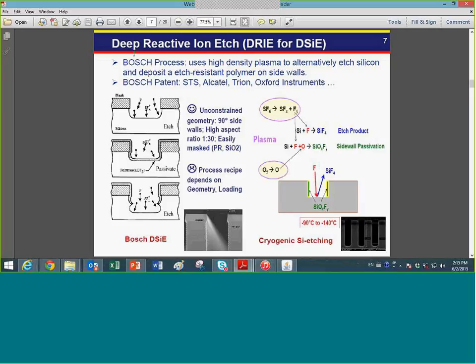The third subtractive process is deep reactive ion etching, DRIE, which allows you to dig deep into the silicon material with a very high aspect ratio, and it has no constraint in terms of how deep you go. For MEMS applications, the feature size is usually relatively big. In our new DRIE system, the Oxford Instruments Astrea 100, you can not only do the Bosch process, we can also do cryogenic silicon etching.